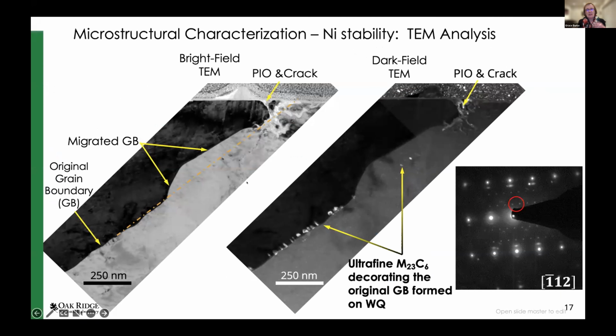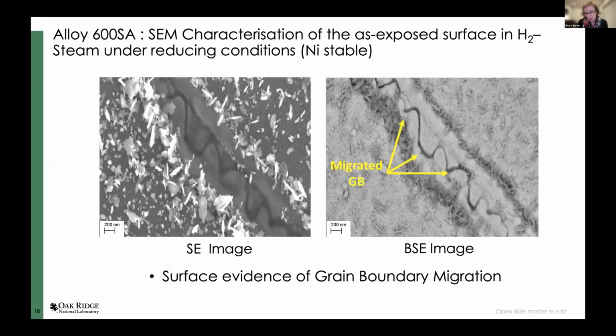So let's have a look at the microstructure of these materials. When we do an unstressed coupon, have a look, do the cross-sectional TEM characterization, we see that we've got some oxide on the grain boundary, and the boundary's moved a bit. Is it migrated? What is it due to? Well, careful TEM characterization, electron diffraction and dark field have shown that it's possible to image the ultrafine M23C6 carbides that had formed on the grain boundary during the water quench, nicely delineating the position of that original grain boundary. So we know that the boundaries are starting to migrate.